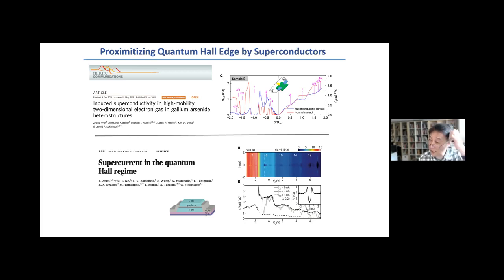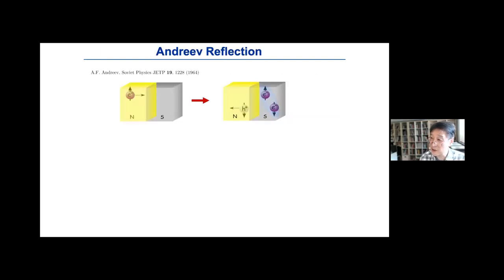Instead of using the Josephson effect, can we really probe the coexistence between superconductivity and quantum Hall physics by showing proximatized quantum Hall edges? One idea here is to use Andreev reflection. We know that in Andreev reflection, when carriers come from a normal metal to the superconducting interface, you can inject a Cooper pair into the superconductor by having holes travel back from the interface. So the idea is, instead of using a normal metal, can I deliver the current through the quantum Hall edge state to the superconductor and detect the holes coming out of this Andreev reflection process?